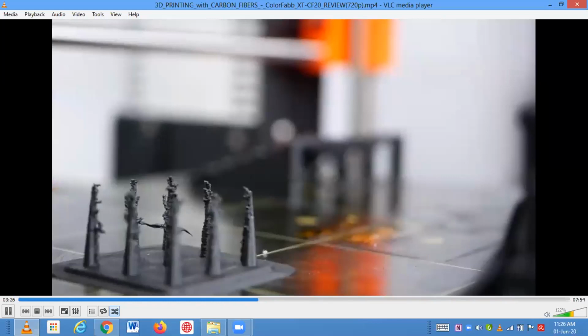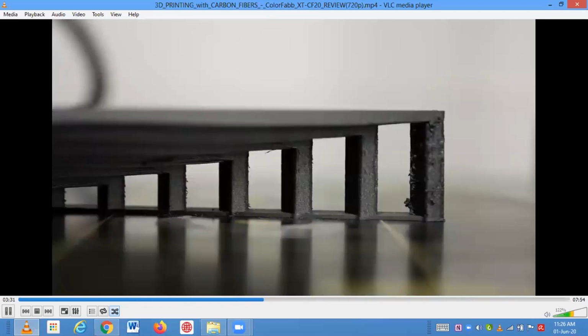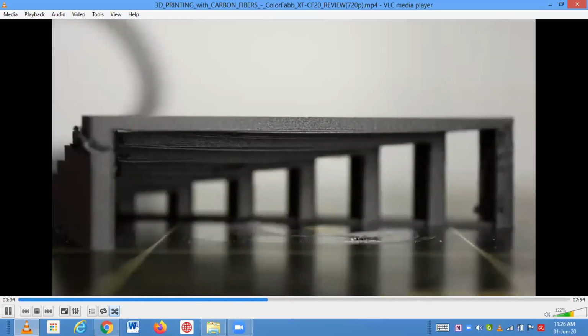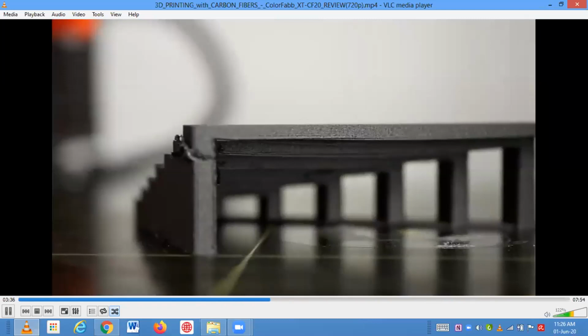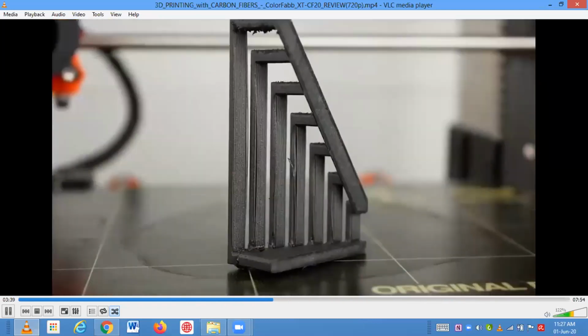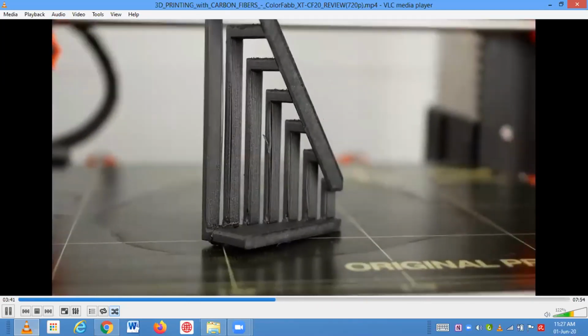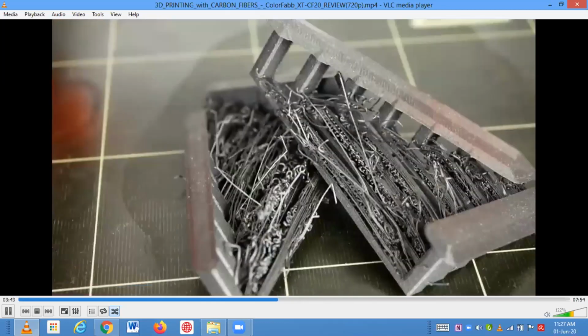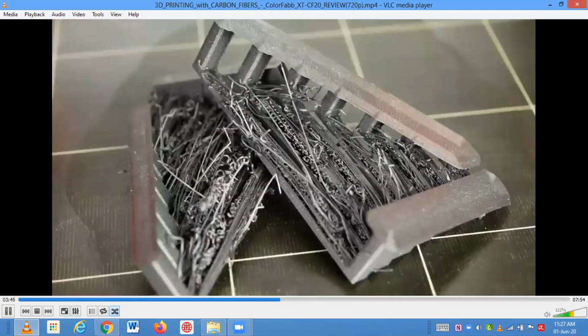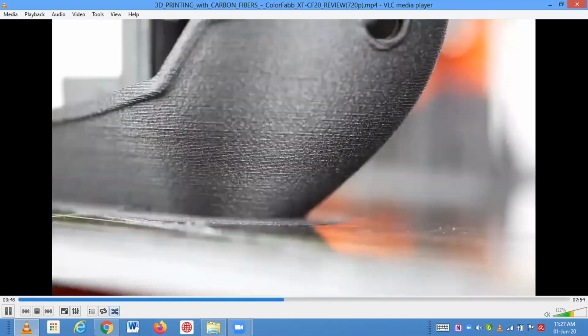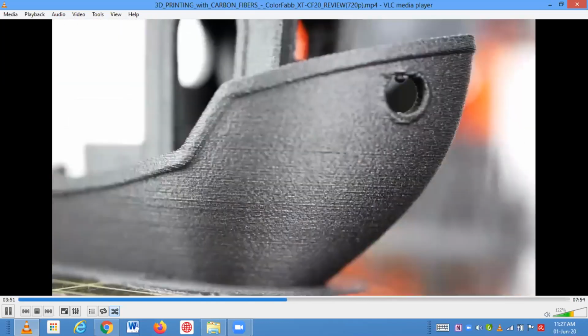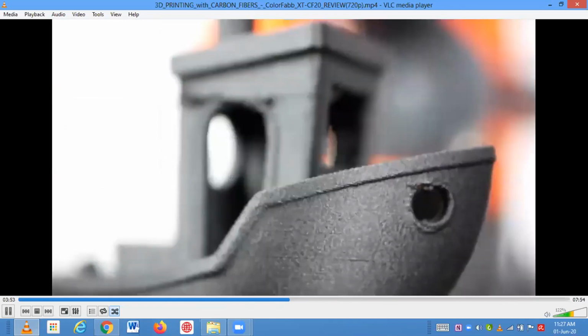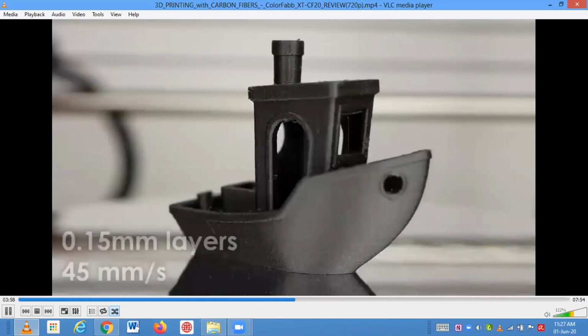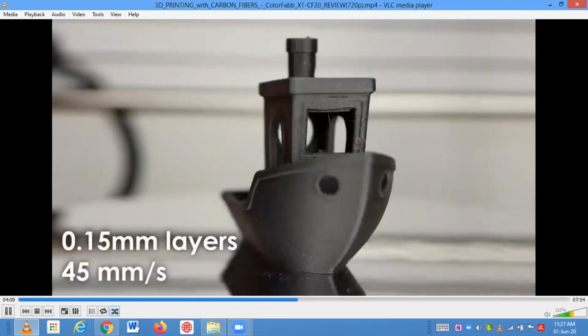Bridging was strange, because at first the part looked really awful. Out of curiosity, I used Slic3r Prusa Edition instead of Simplify3D, which made such a difference. Almost perfect bridging, even at the largest gap. I tried to tune the settings in Simplify3D, but nothing I did improved the print quality, which is really strange. The 3D Benchy reflects these results because it showed the blobs at the retraction points and some material bits at a couple of places. Still, if you overlook these, then the rest of the boat looks stunning with the matte black finish.